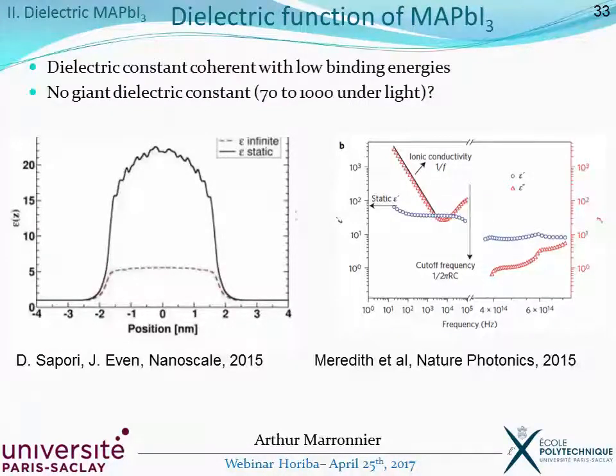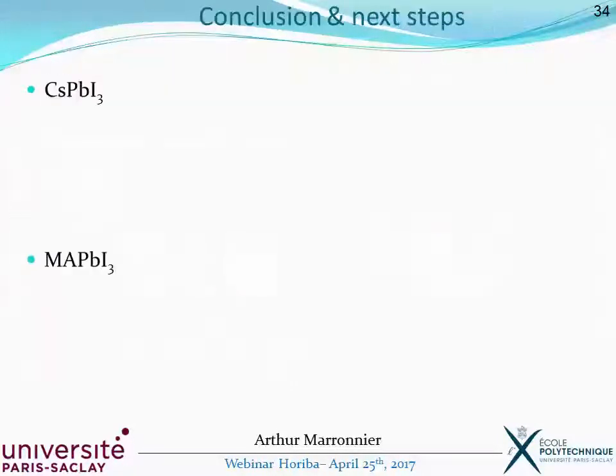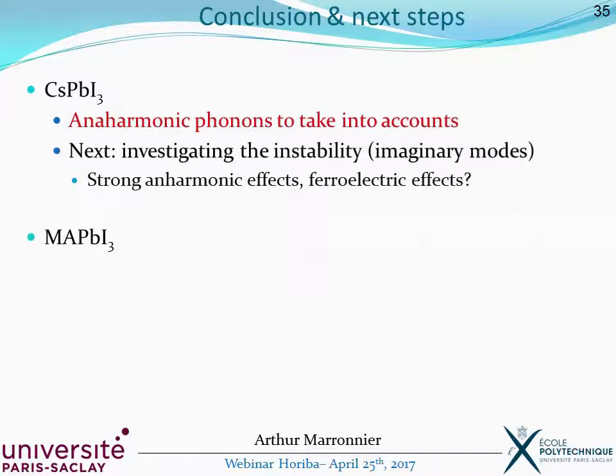We did not find any giant dielectric constant as it was predicted in another article in 2015, also from calculations, where they predicted some very high values, 70 for example, for the static epsilon. And as a general conclusion, we've seen that in the cesium inorganic perovskite, we have structural instabilities that have to be taken into account in order to correct the values of the dielectric constant. And that's the next step that we are investigating right now, investigating these instabilities, these anharmonic effects, which could be at the origin of the ferroelectric effects in these perovskites.